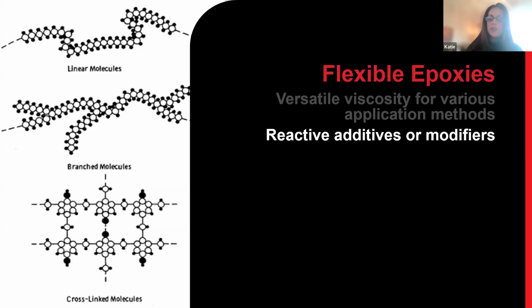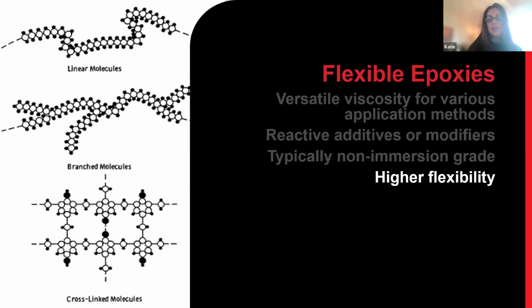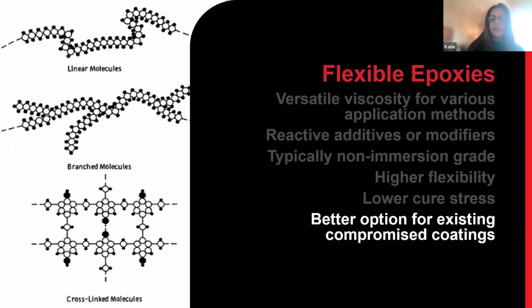So you can see to the left that certain cross-link patterns, which may be good for permeability, can lead to more rigid films. Altering this cross-link pattern can allow for more flexible films. And this is why these types of coatings, which may have very good chemical resistance, may not be the best choice for an immersion grade coating or liner. But just as the coating says, it does offer higher flexibility. It provides lower cure stress, and it's a better option for existing or compromised coatings.